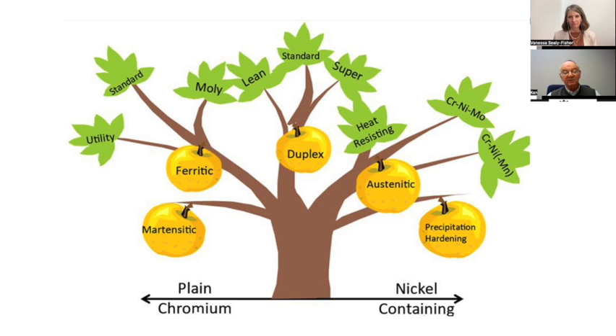The corrosion resistance of the martensitic family is in line with their chromium contents, and it might range from about 11% up to about 18%. Mechanical properties, which come from the heat treatment, combined with their corrosion resistance, is what provides the useful attributes of this family of alloys. And so you get grades and applications which range from wanting wear resistance from the material, or keeping a sharper edge, such as for knives. Alternatively, you might be looking for high strength, like in valve spindles and pump shafts. So in summary, that's the martensitic branch of the stainless steel family.